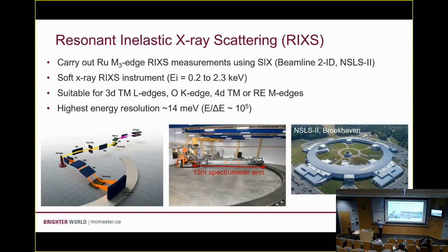For this energy range, if you have materials based on 3D transition metals, you can do L-edge RIXS. If you have oxygen, you can do K-edge RIXS. And for 4D transition metals like ruthenium, you can do these M-edge experiments. Okay? Which edge you go to will define which selection rules are going to apply in your experiment, or whether you're directly probing the valence levels or not.